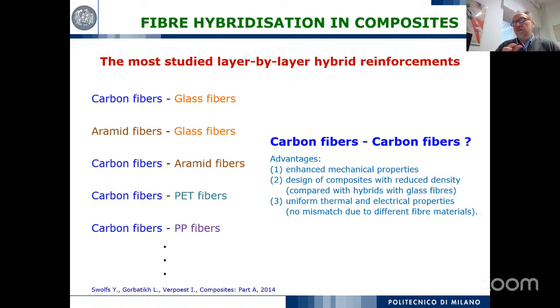two carbon fibers of different quality. This results in this pseudo-ductility, and the main reason for this is that if you use the same fiber or the same material for the fiber, this will, from one side, enhance the mechanical properties because we are using carbon. On the other side, we can reduce the density because of this fiber. And last but not least is the uniform thermal property and electrical property, and so we do not have mismatch in the material.